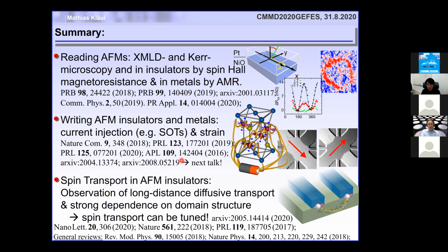And so we measure that by putting platinum on top, and then you go to the spin flop and you see the reorientation. What is quite crucial is that these systems usually are not very inert, so they start to oxidize at interfaces. So one of the things that is quite important here is that you do the flaking in a glove box and then transfer inside the glove box into the UHV chamber. We have a UHV chamber which is directly connected to the glove box, so they never see air in between.